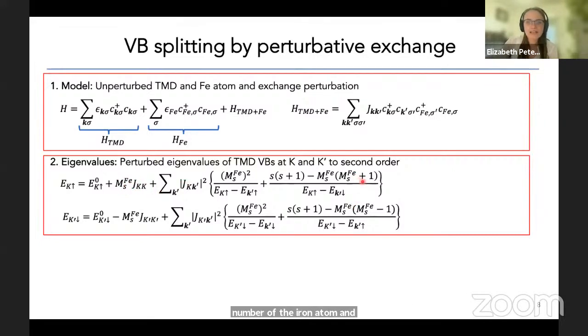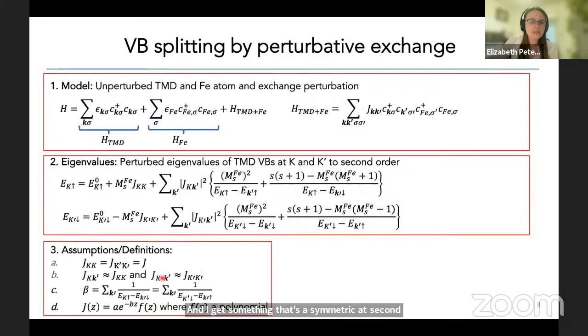And I get something that's asymmetric at second order. And I make a number of assumptions. First of all, I assume that the exchange parameter at K and K prime are the same, which makes sense if you consider hydrogenic orbitals and you consider the fact that at K and K prime, the topmost valence band orbitals are dxy and dx squared minus y squared orbitals. I also assume that this J goes as an exponential decay times a polynomial, which makes sense again if you consider hydrogenic orbitals and their overlap.